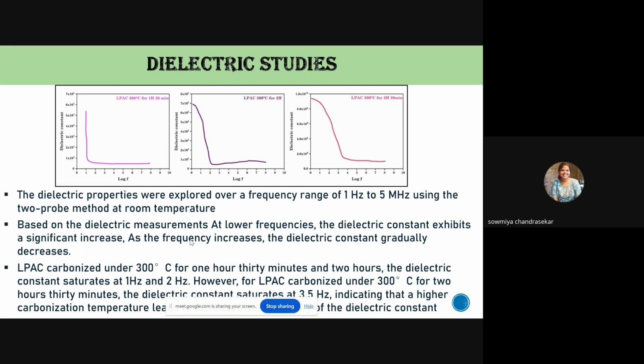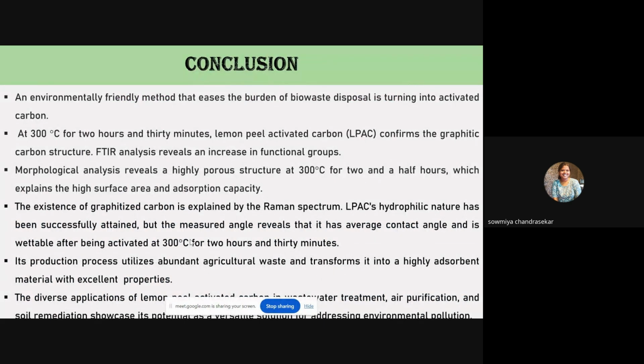Then I would like to conclude. Turning bio-waste into activated carbon is an environmentally friendly method that eases the burden of waste disposal. At 300 degrees Celsius for 2 hours 30 minutes, lemon peel activated carbon confirms the graphitic carbon structure. FTIR analysis reveals an increase in functional groups. Morphological analysis reveals a highly porous structure when treated for 2.5 hours, which explains the good absorption capacity. The existence of graphitized carbon is explained by the Raman spectrum.